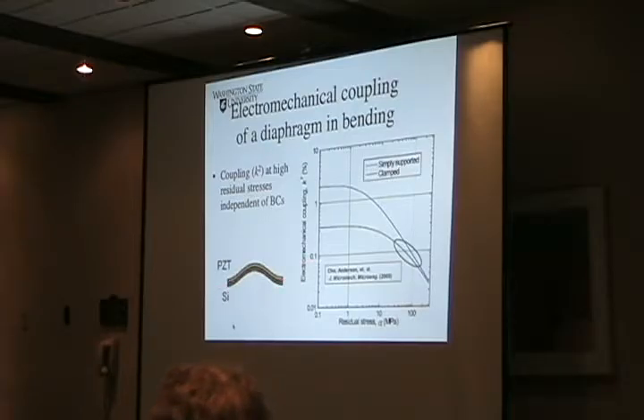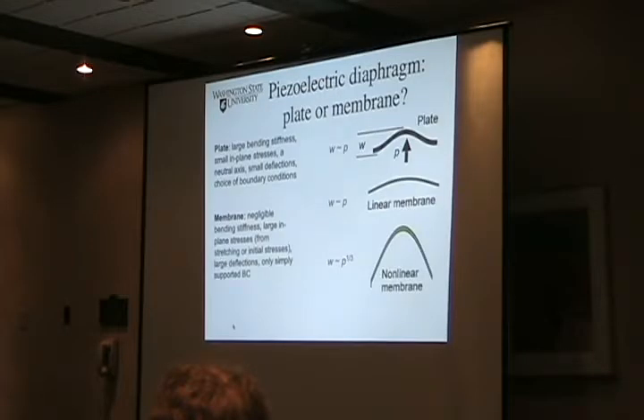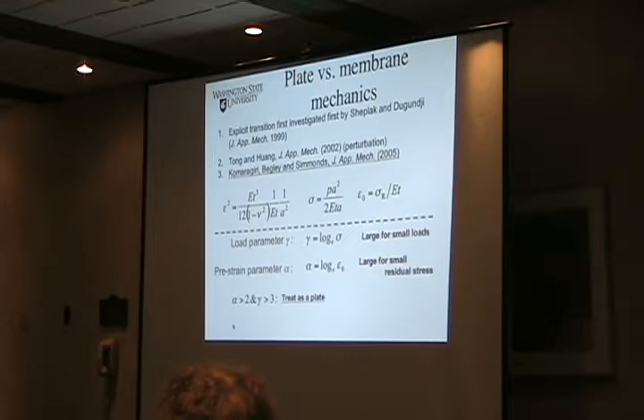Effectively, if we were bending the device, which is what we do for this kind of plot, the device has to have this kind of shape. But we actually pressurize it out so that the deflection goes as the pressure to the 1/3 in this case. We have negligible bending stiffness, and basically we have a large in-plane stress. And so it led us to think, well, maybe we're looking at this wrong. Maybe we shouldn't model things like this. Maybe we should model as pushing out on balloons instead of pushing out on plates.